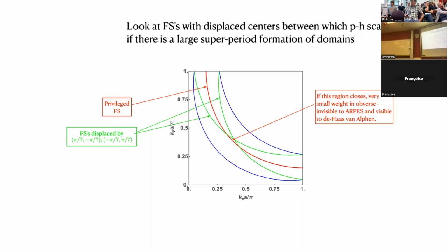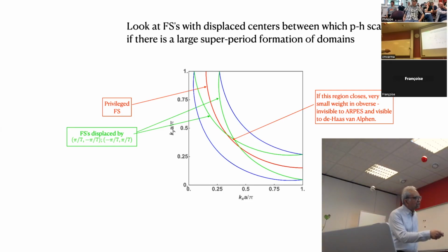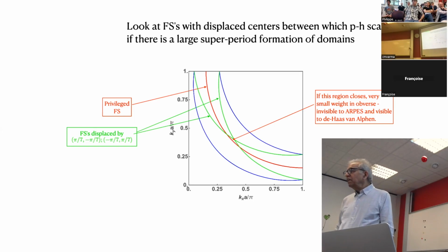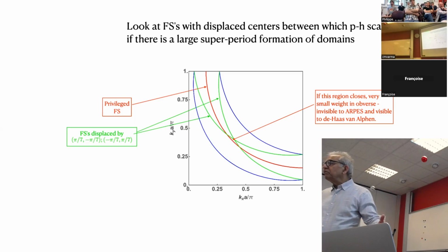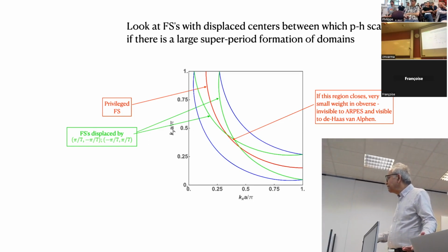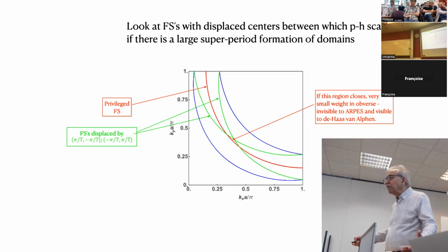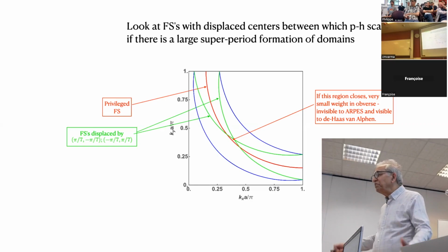Enough of those drawings. And now I can only scatter from below the Fermi surface to above, and you can show that if this fellow has one of those orders, that in this direction, the matrix element for scattering is 0, and it increases as you go across here. So now let's look at this little pocket. I can scatter from the occupied to the unoccupied part here, and this scattering increases as I go towards the end. Net result is, now after this is a 1 electron calculation. So no magic is required. You just have to do a sort of complicated second order perturbation theory calculation, or just diagonalize a finite matrix.